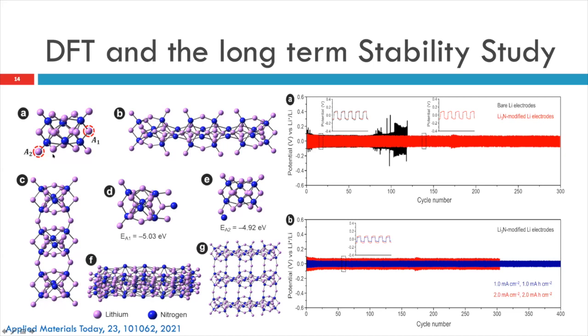And when you do symmetrical studies to see whether the surface film is actually working for us, the black color you see in the plot is only bare lithium, which is not modified. With the modified one, there is no deterioration. The passivation film is actually working for a large current, even a lower one. If you see the large current to the even lower current, both are working fine.